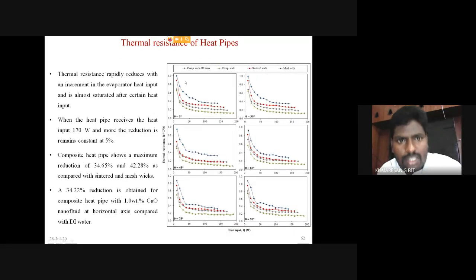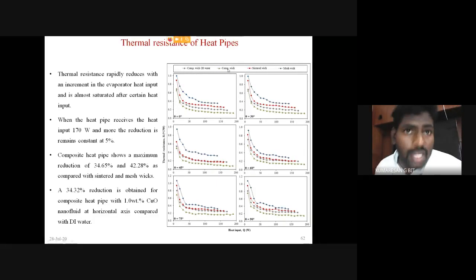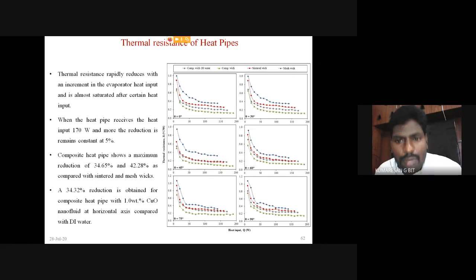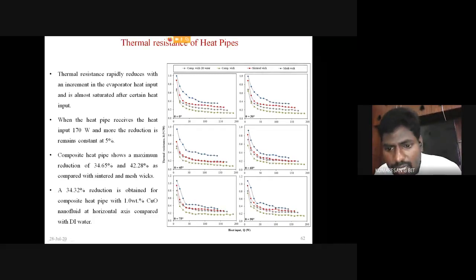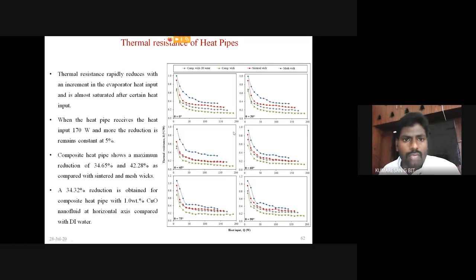Then this was the thermal resistance of heat pipe. You see here that the composite wick heat pipe operating with 1 weight percentage of copper oxide nanoparticles registered the very lowest thermal resistance value irrespective of the inclination angle. You see in all these 6 figures that the thermal resistance of composite wick with 1 weight percentage of CuO nanofluid registered the lowest value. Likewise, in the previous